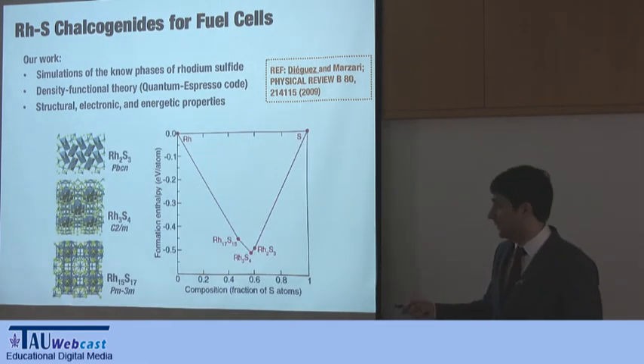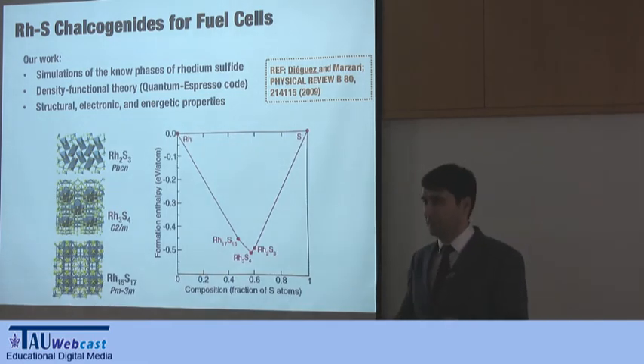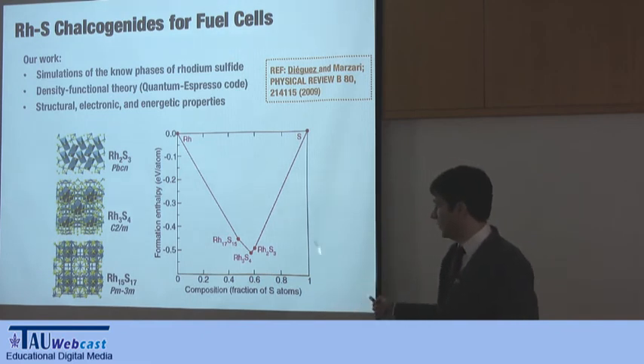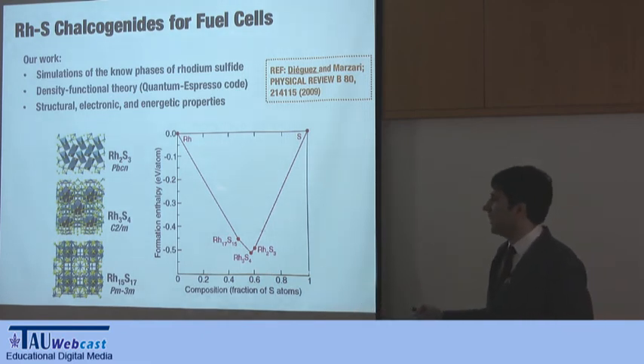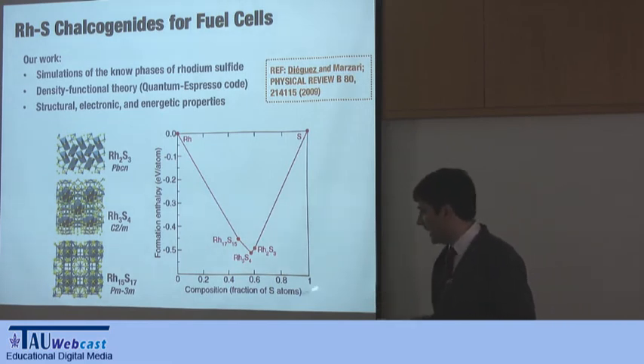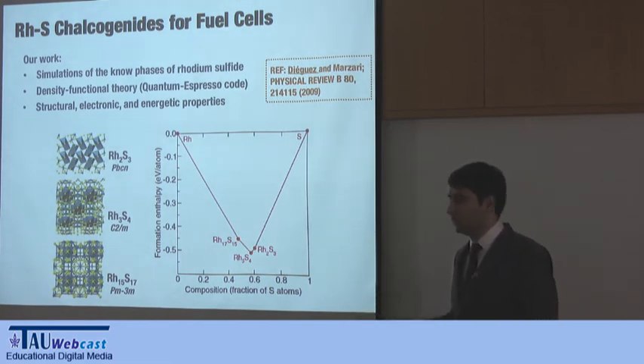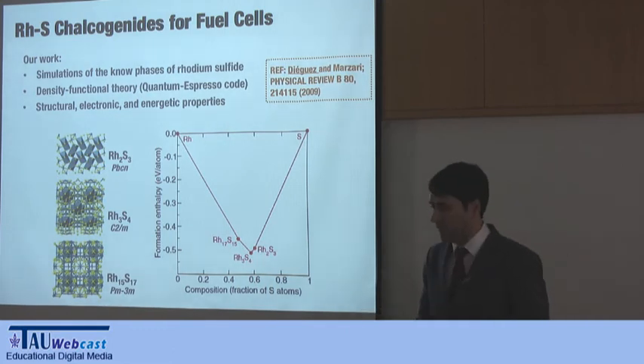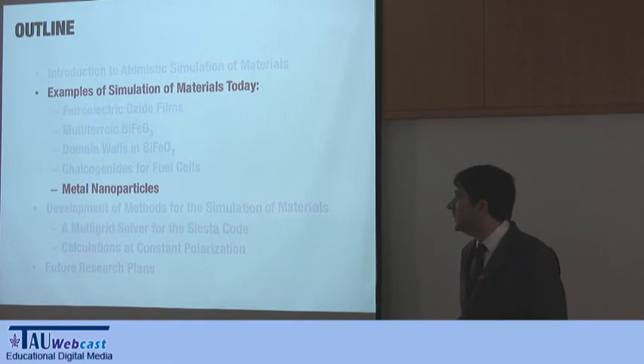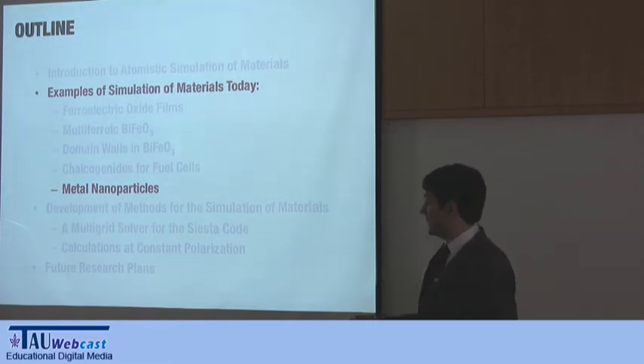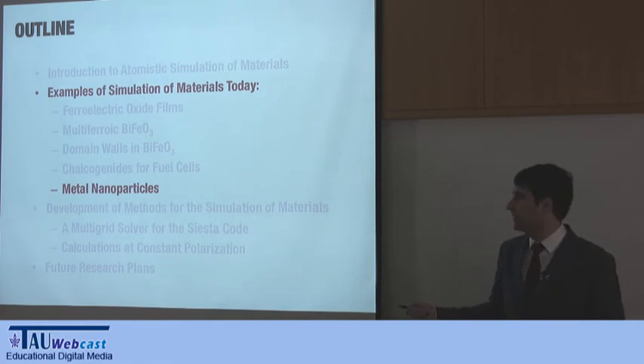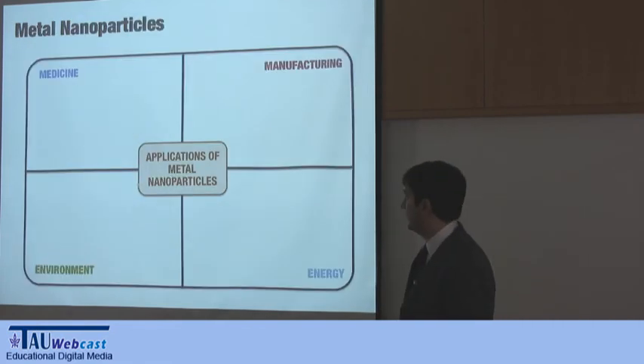You can compute, again, energies, structures, and in this case, for example, you see that the compounds are in the convex hull of this diagram, so you expect them to be stable, and in fact it seems that the three of them appear in the nanoparticles they use. At the very beginning of, the first project that got me interested in DFT things had to do with metal nanoparticles.